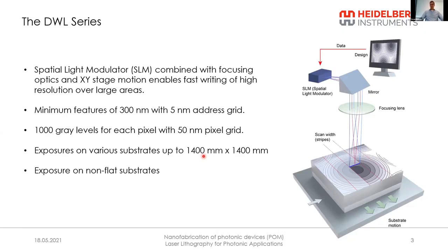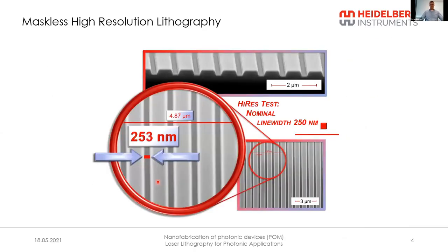In the field, we have a number of systems that go up to 800 millimeters, but in theory, we can do 1400 millimeters. It's also possible to expose non-flat substrates. I will tell you about this a little bit later. When we look at the resolution, as I said, we specify 300 nanometers, but if you just write simple lines like these, you can even go a little bit below this. So this is something like 250 nanometers that we achieved in a standard 300 nanometer thin resist.